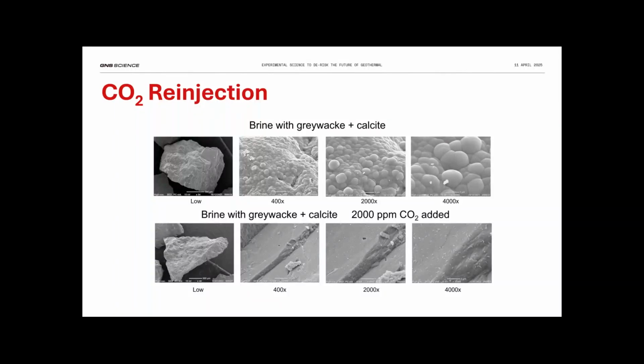And it's a win-win-win because you're getting rid of the CO2, you're stopping the silica scaling, but it also dissolves the calcite out faster than the brine without CO2. Because of the acidity, the calcite in the rock actually dissolves faster. And so it's basically acting as a cleaning agent of the formation. It actually dissolves the calcite out of the formation, which is the culprit that's causing your silica polymerization.